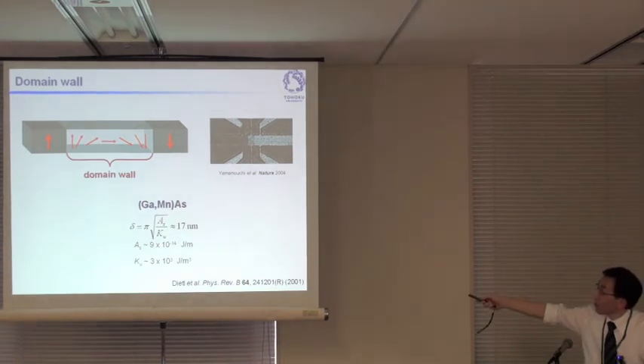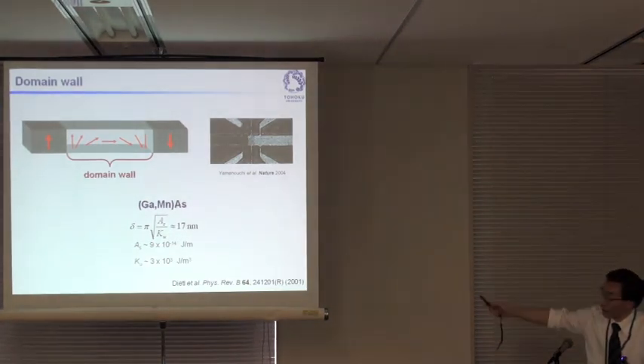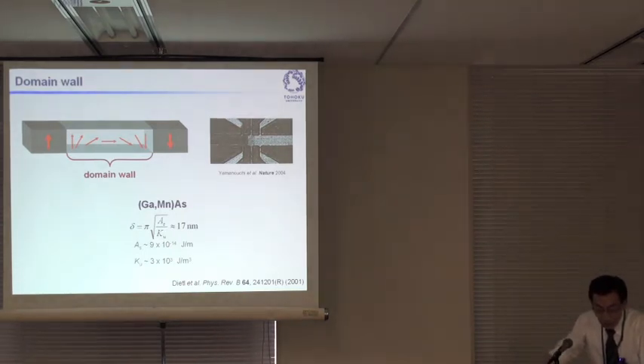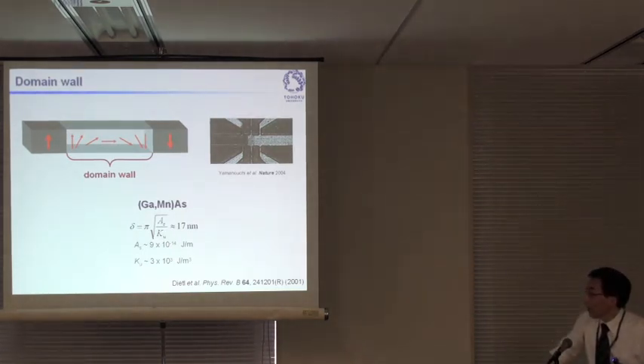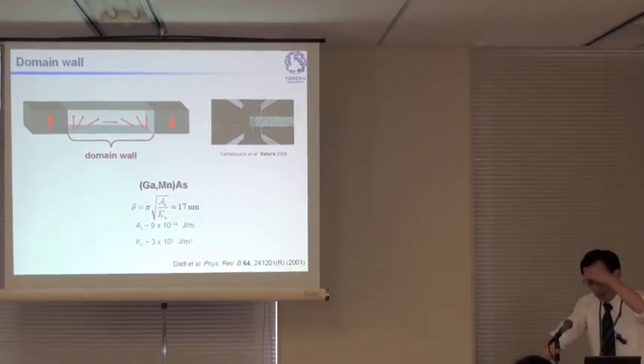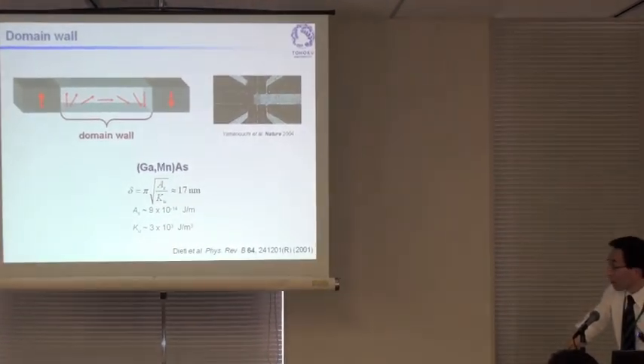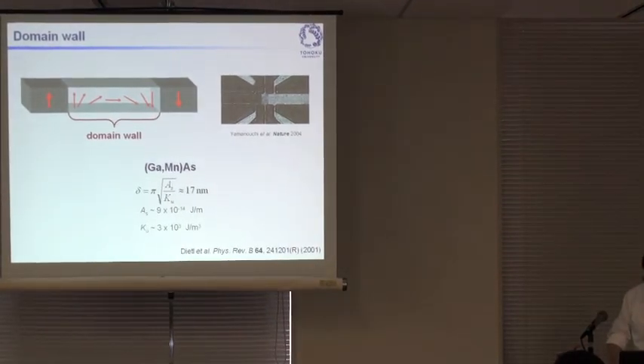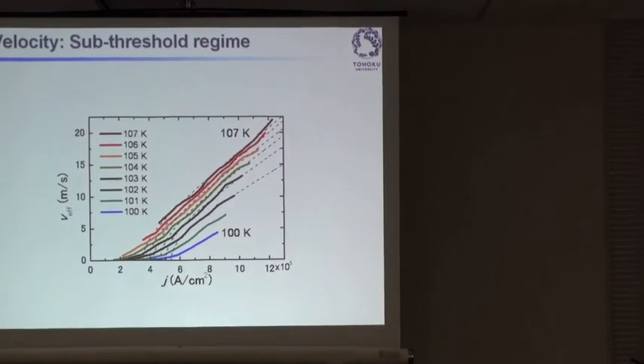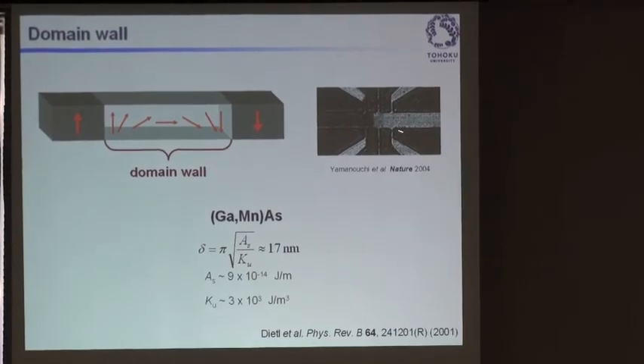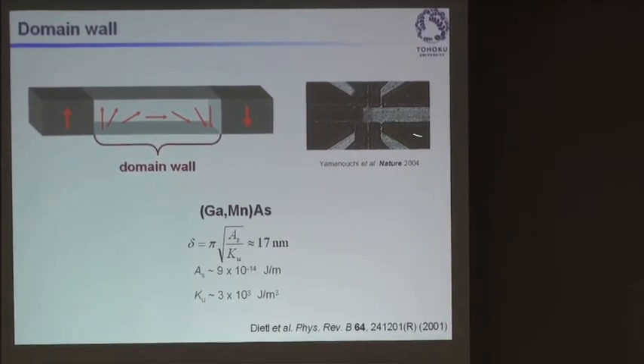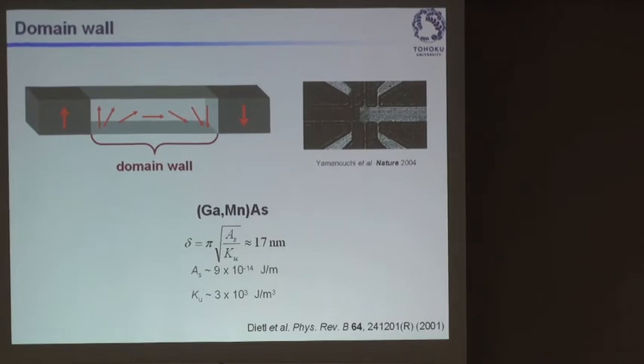We haven't been able to visualize the domain wall, but the position of the domain wall has to be here. And this domain wall gives you a number of physics, like the spin transfer physics that Dr. Yuasa discussed. As a result, you can drive current through, for example, this wire part. We have gallium manganese arsenide here, and we have a domain wall here. We pass current through this domain wall, and we can observe the domain wall motion.